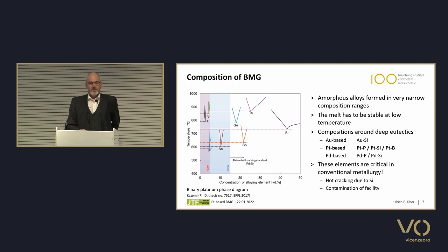Now, to reach these special properties, we have to use special compositions. We heard in the presentation from Chris Corti that some elements are not really beneficial in jewelry alloys. For instance, high amounts of silicon, germanium, phosphorus. But especially these elements are interesting to make bulk metallic glasses, because what do these elements do and why are they usually critical? They form so-called low-melting eutectic compositions. So this diagram shows sections of phase diagrams. So it's a collection of different binary phase diagrams, and it shows the reduction of the melting point by this element.